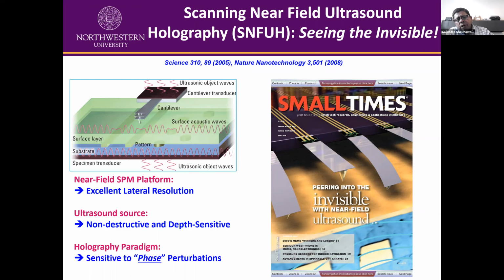But then later on, we came up with another technique. Rather than oscillating the sample, we are also oscillating the probe simultaneously at two different frequencies. We use piezo crystals to excite those out of plane vibrations. The cantilever is basically a reference cantilever because it's made of the same material, so the frequency will not shift. So when these two oscillating objects interact with each other, they create a difference frequency. And that frequency is low enough that the cantilever can easily pick up those modulating waves, and we can extract the subsurface information, because when you excite the sample, if it has any defects underneath, it can delay the phase. It can change the phase of that wave that's reaching the surface. So basically we are measuring the change in the phase. So it's non-destructive, it's depth sensitive, it has pretty good lateral resolution, and it's very sensitive to phase perturbations.